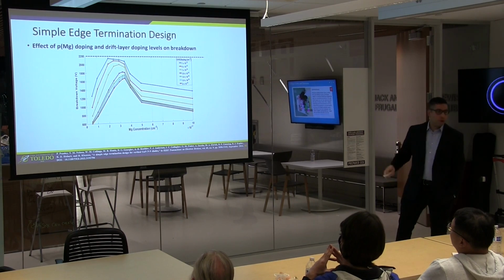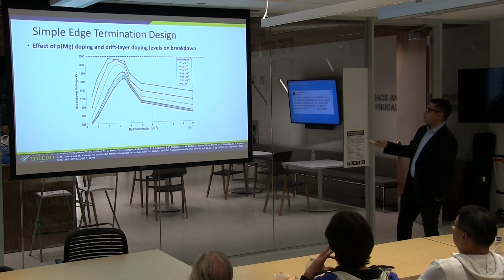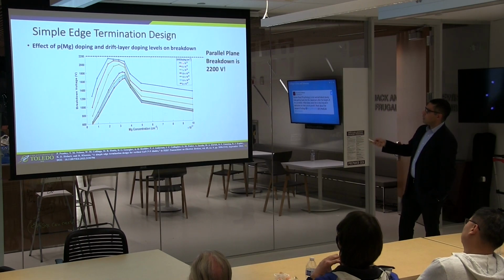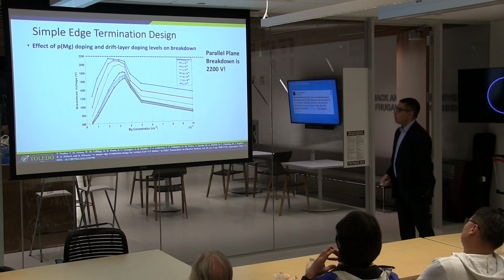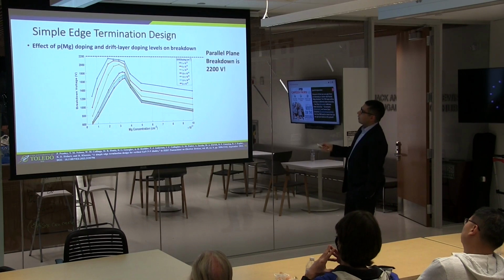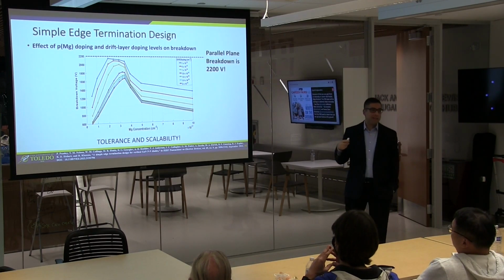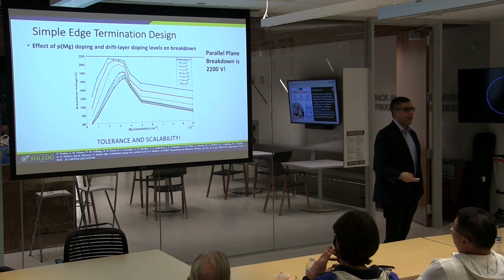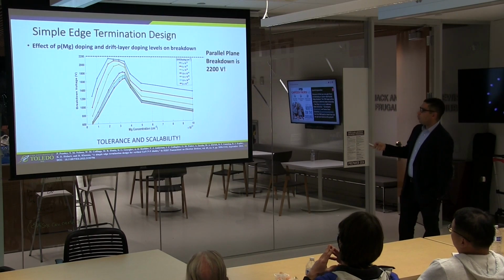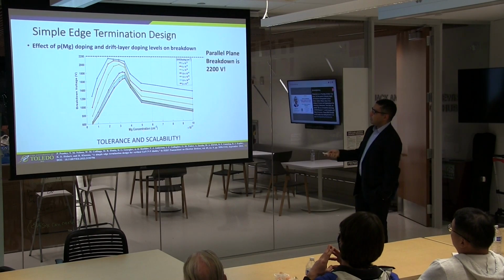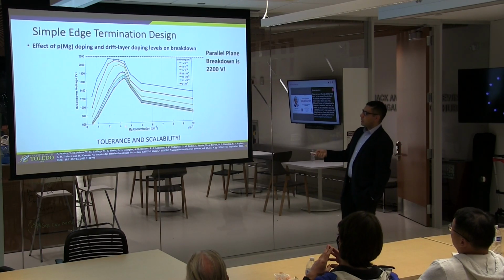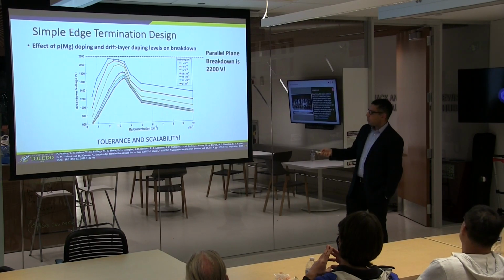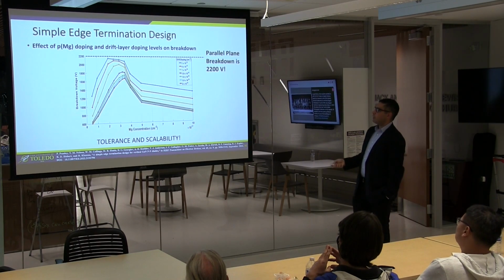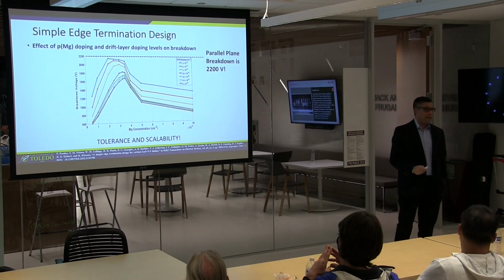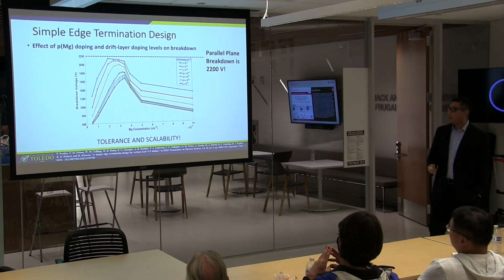And we varied the drift doping. I call your attention to this blue curve here. The blue curve is at 1 × 10^15 drift doping. And the parallel plane breakdown, what the simulation predicts is the most you can get out of that structure, is 2200 volts. So what we're saying here is that for significant changes in p-GaN doping, a 100% change from 2 × 10^17 to 4 × 10^17, you're getting roughly the same amount of breakdown voltage out of this material, out of this device.